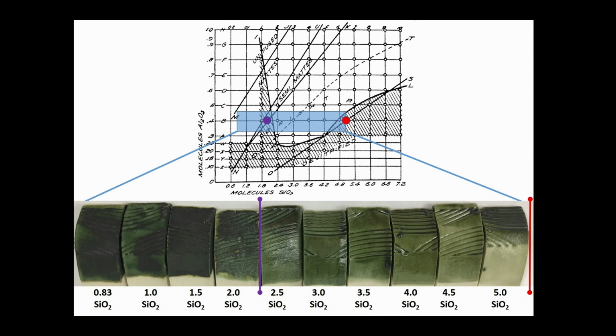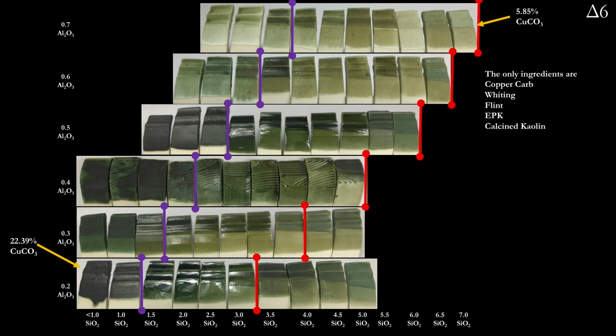But as you can see, we have gloss tiles where we're supposed to have gloss. On the left-hand side, where we have the purple dot, the tiles start to dry up pretty quickly towards the high alumina area. And on the right-hand side, our last tile reaches just a 12:1 ratio, but as soon as we reach 12:1, the tile starts to dry. This is our first set. We think this looks great, so why don't we go ahead and cover a larger area of the map? And that's exactly what we did, and you can see it here.